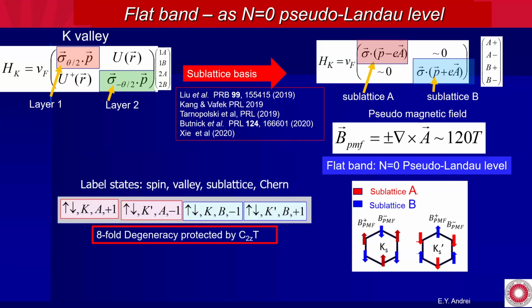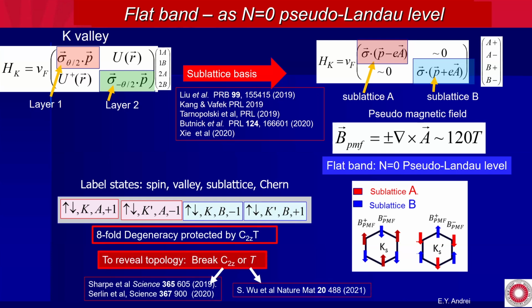So now we can write these 8 states. We can label them by spin, valley, sublattice, and Chern, but they're all degenerate. So there is topology inside this flat band, but you cannot see it because it's hidden inside this degeneracy. And this degeneracy is very strongly protected by C2Z inversion symmetry in plane and time reversal. So unless you break those, you will never see any interesting correlated states. You have to break those. So one way to break them is to break the inversion symmetry with a substrate, as I'm going to show you in a moment. The other one is, of course, to break the time reversal symmetry with a magnetic field.